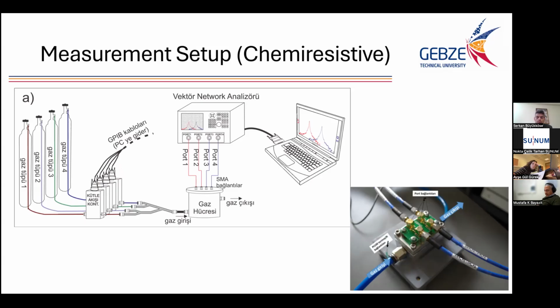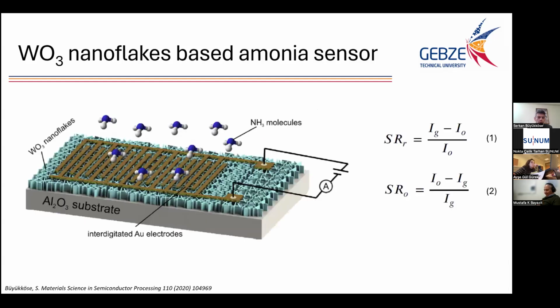So let me show you one of our works. Here, what you see is an alumina substrate with nanoflakes on top. Here, the interdigitated electrodes are made by shadow mask, directly evaporating the gold structures. And here you see the formulation for the sensor response. The sensor response for reducing gases is defined by equation 1, and for oxidizing gases, it's defined by equation 2.